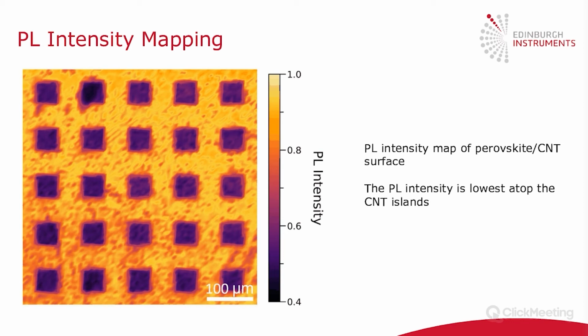So this is direct proof, or at least an indication, that we've got efficient hole extraction out of the perovskite layer, because you can see this drop in PL intensity occurring on top of the carbon nanotubes.